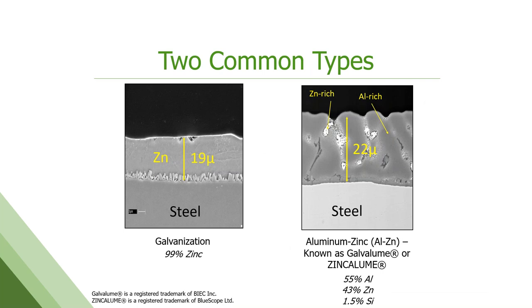Here, this is at a microscopic level, what we're talking about. On the left is just hot dip galvanized, and it's all zinc. The little crystalline structures here are where that zinc layer alloys with the steel and bonds to it. On the right is Galvalume or ZINCALUME product. In this, the gray area, which sort of looks like brain gray matter, is the aluminum. Because it's by weight, and aluminum's density is quite a bit different than zinc, you end up with a lot of aluminum by volume on the strip. So that's the bulk of it.